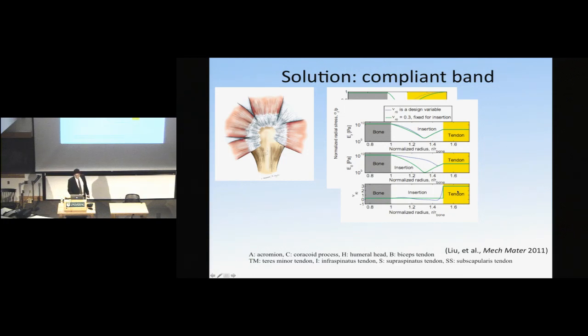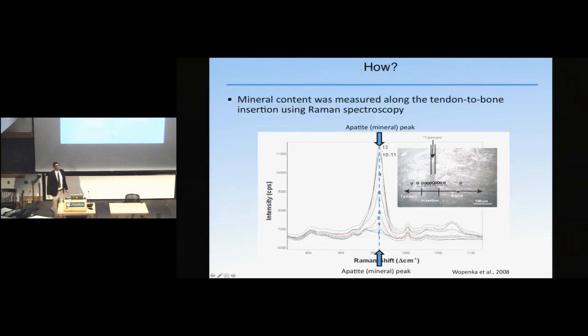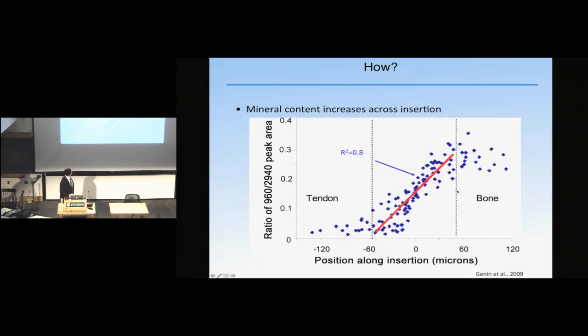So the next question we asked is, how does the body achieve this compliant region? And so the first try would be to come up with a replication of those properties. And so we used Raman microprobe spectroscopy to get a spatial distribution of mineral between tendon and bone. And I won't go into the details of how that works, but what came out was this, which is that between tendon and bone, if we analyze the Raman data to estimate the volume fraction of mineral phase, this dip in stiffness comes despite a linear increase in the amount of mineral. So stiffness goes down even though mineralization goes up.